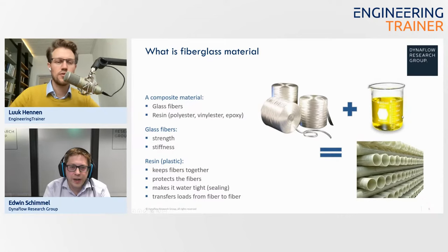So we have the glass fibers. How long, Edwin, would such a curing process typically take? It depends a bit on the type of resin, but with epoxy, if you have produced the pipe, it's of course still a viscous liquid, and you cure it for 3 hours, and then you have baked your pipe, so to say. But with polyester or vinylester, it cures faster and with less heat.